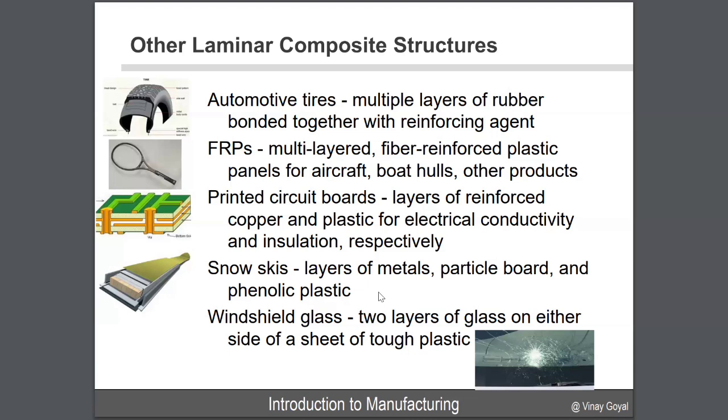It's not fully cured. So that allows you to cut it, kit it, we call it kitting, and you put it down layer by layer. You vacuum bag it, and then you put it into the oven with a cure cycle. You apply pressure as well to remove any porosity, any voids, and that process gives you a composite system.